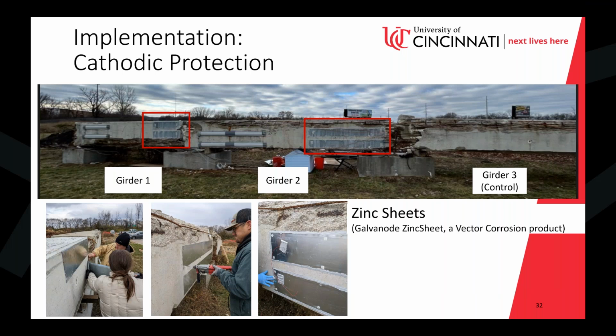And the idea here is the first one is just a zinc sheet. It's applied as you would apply tape to something like masking tape. There's a special adhesive behind it. So you cut it and you roll it out and you literally stick it or paste it onto the girder surface. That's going to basically complete one side of that circuit potential. So now that is through the concrete, making the ionic connection. And then you attach wires to it just simply via welding to complete that connection. In our case, we just attached them to the free strands on the outside of the girders, which had been broken apart. So that's the application here.